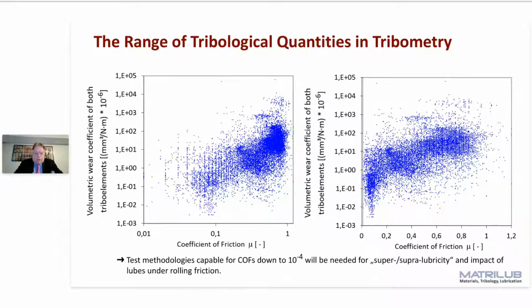To give you a range about the quantities you measure, they are shown here on the left side on a logarithmic scale for the friction, and on the right side on a linear scale for the friction. These were taken from a database with 19,000 test results. The first point you see, and that's why you have so many different test equipments around, is that the wear rate goes over orders of magnitude, at least 7, 8 orders of magnitude. And it is clear that one test equipment can never cover such a large range in terms of wear rate or in terms of wear resistance.